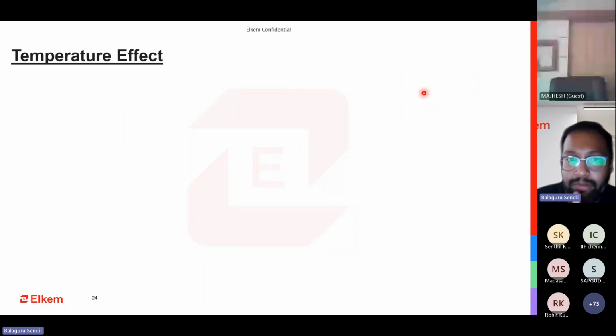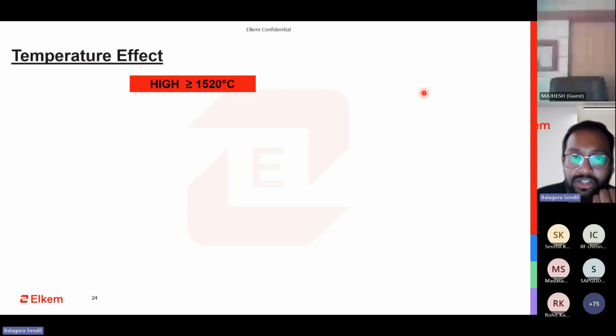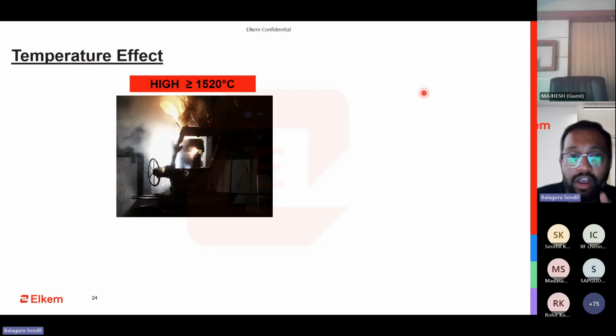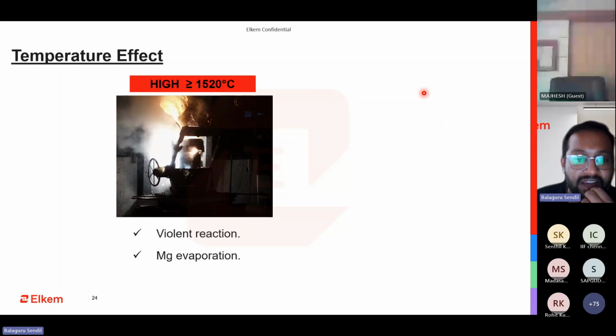And the next one is the impact of temperature. If it is more than 1520 degrees Celsius, this could be because if you have to pour for longer, you cannot afford to have the end of pouring less than 1350 or 1360. So what we do is increase the tapping temperature to the higher side. What happens there is you have very violent reactions. If you are not using the correct FSM, or if you're using a high amount of ferrosilicon magnesium, with incorrect calcium value, then the reaction violence is extremely high. It consumes more energy. Most of the Mg just keeps evaporating out, your yield is on the lower side, and then money is lost.